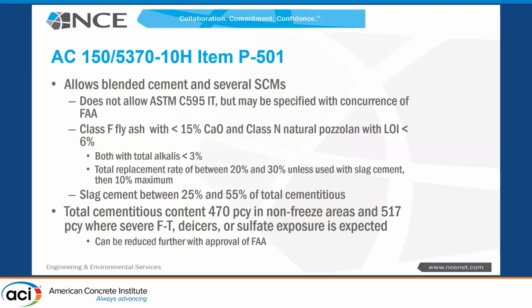Basically, they have their fly ash specs, but they encourage the use of fly ash at 20 to 30% replacement, and unless used with slag cement, then 10% max. You can use up to 55% slag cement. And they allow you to go as low as 470 pounds per cubic yard, unless in a freeze area where they say 517, but they'll let you go lower if you petition them.